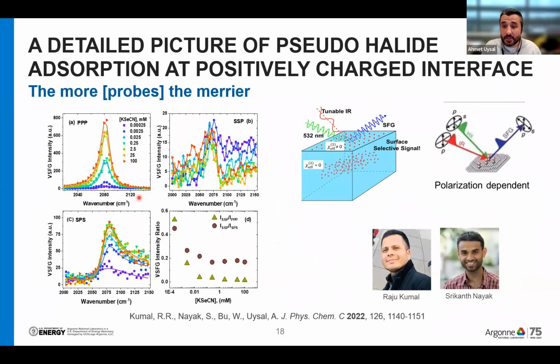We can look at the CN stretch, as I mentioned, and we can do it in multiple ways. We can control the polarization of the laser, and by choosing different polarization combinations, you get sensitive to different orientational ordering in the SFG. And that's the tricky part. SFG is not only proportional to the number density, it is also sensitive to the orientational ordering.